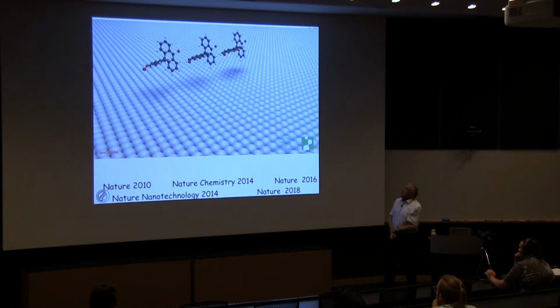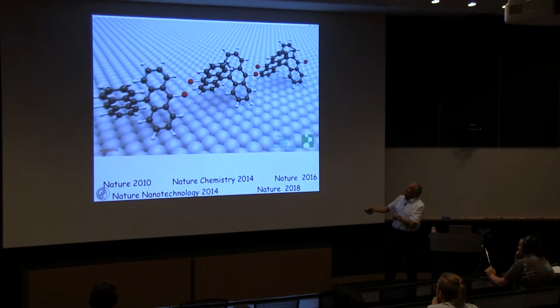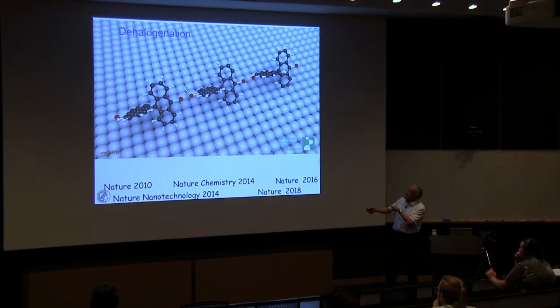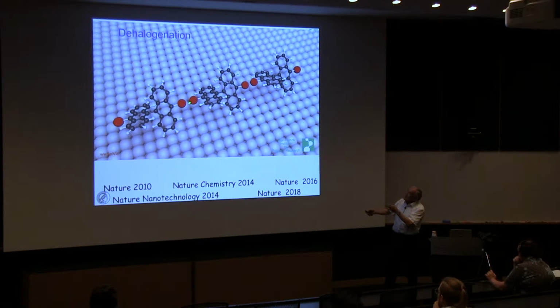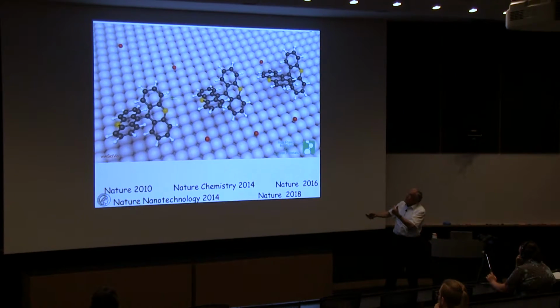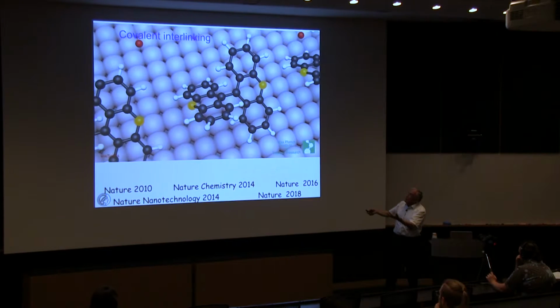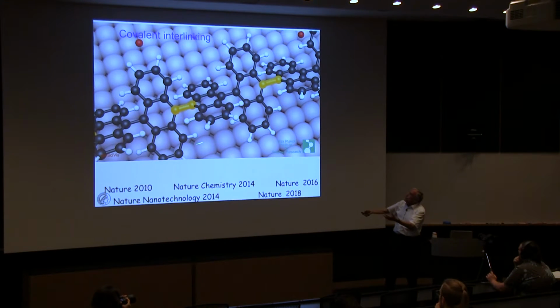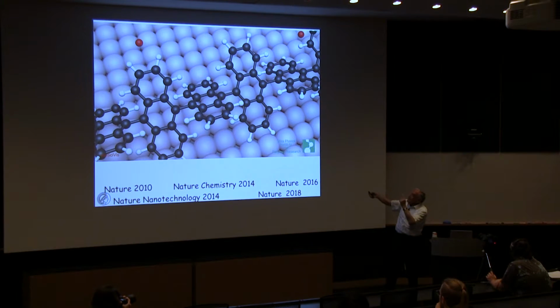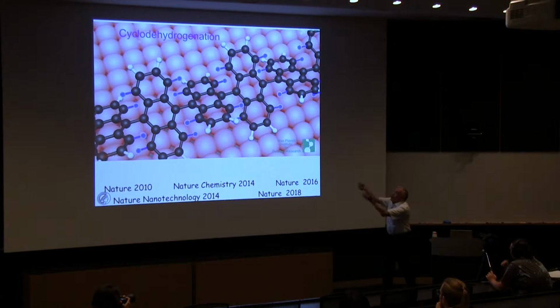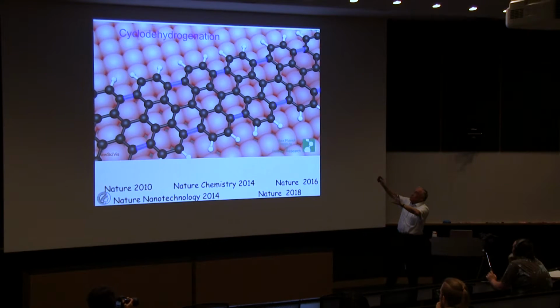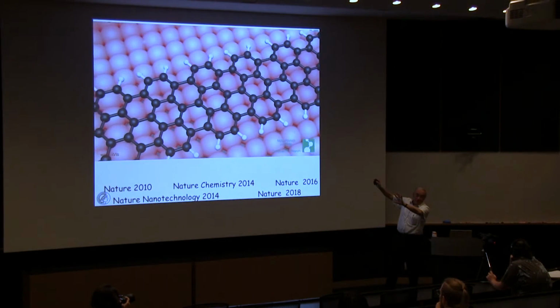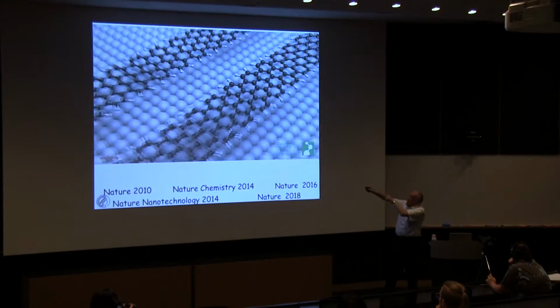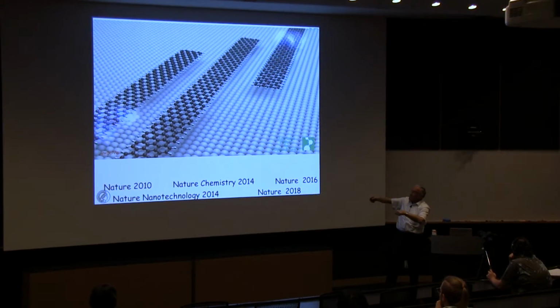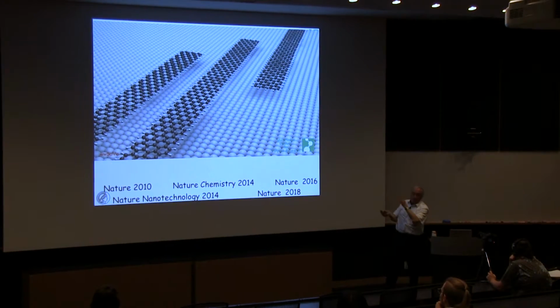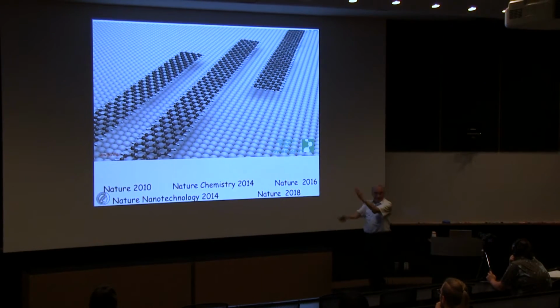We have a monomer, very carefully designed. We put it on the surface from the gas phase. We clean that. There is a diradical, you know that word. It polymerizes, and in UHV, there is nothing to disturb that. We zip it up into a polymer, and I told you, the precursor is non-planar, and then by a heat-induced process, we make the graphenic structure. And I will tell you later that these ribbons are more important than the graphene itself. That is, when you do it on a high Miller index surface, you have them side by side.